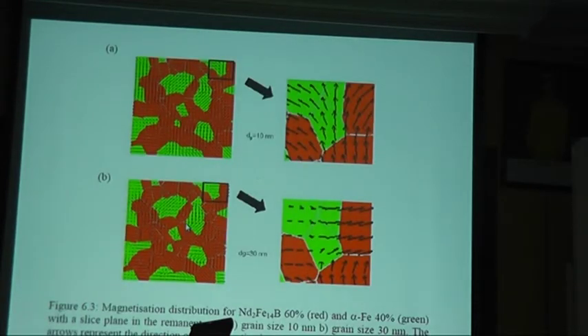This is another example of magnetization distribution and magnetization configuration for 214-1 60% and alpha iron 40%. The grain size, we can play around, we can control the grain in the micromagnetic solver, which we cannot do in real. How can we control? We want 10 nanometer, we want 30 nanometer, we can't do that. But here we can do that, then we can study the exchange coupling.